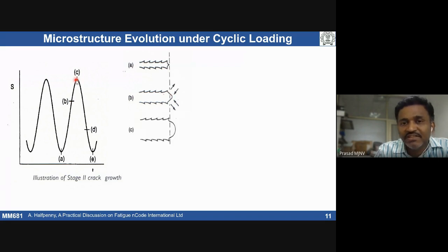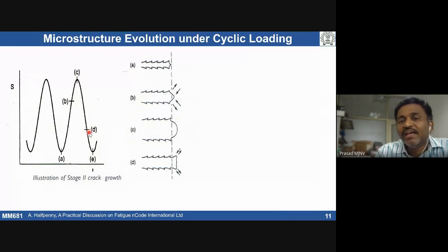When I apply the stress up to C, the maximum stress, the crack front is going to bulge like this. Once I drop the stress from C to D, again you are going to see shearing activity in the opposite direction. But already the crack has moved from this location to here. When I drop the stress to the minimum stress, the shearing activity takes place in the opposite direction. That can lead to some blunting. The crack can get blunt.